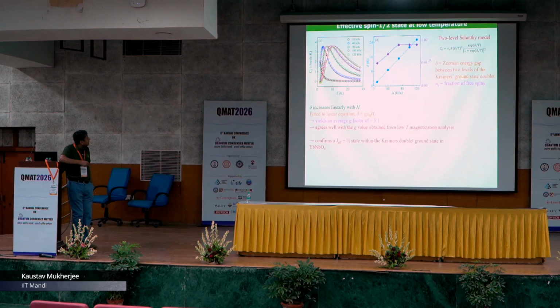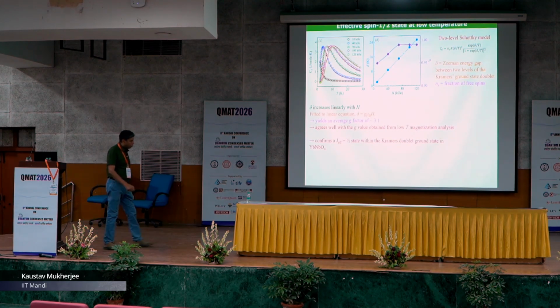Now, we obtained the Schottky anomaly contribution to the heat capacity as a function of temperature, and we fitted it with a 2-level Schottky model, and all these values give a Landé factor of around 3.1, which is in good agreement with the values obtained from the low temperature magnetization analysis. So, basically it confirms a J effective half state within the Kramers ground state doublet in YbNbO4.